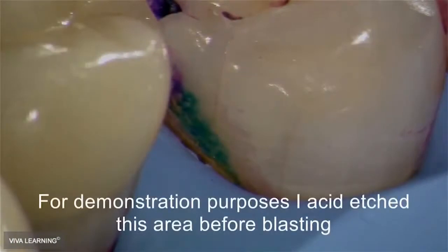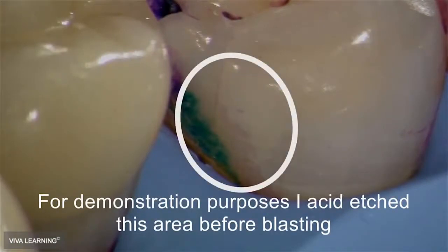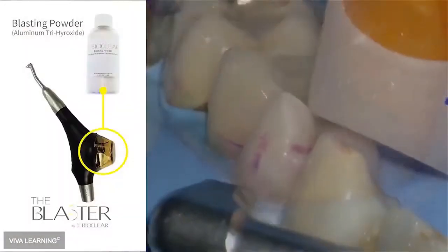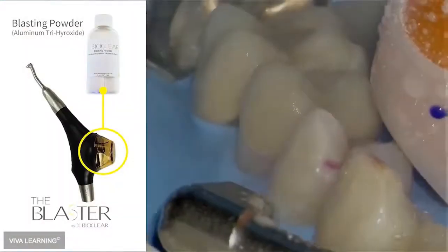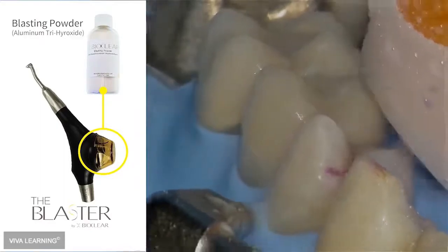This is really interesting. I actually went in and put acid etch on that spot right there and waited for 20 seconds. You can see that phosphoric acid does not remove biofilm. Let me repeat, phosphoric acid does not remove biofilm. So if we're going to have an infinity edge, we have to go in, disclose so we can see what we're doing, and then blast this. This is a BioClear blaster with aluminum trihydroxide.